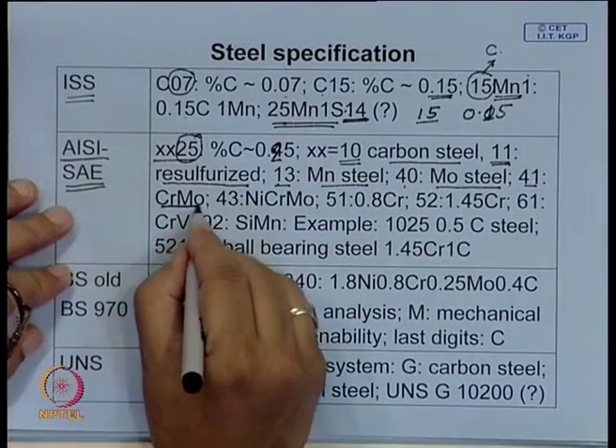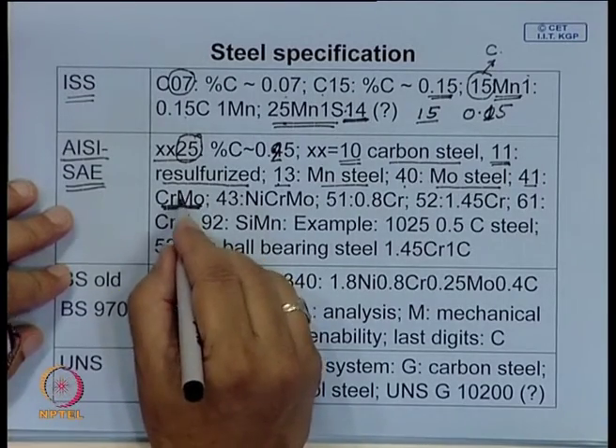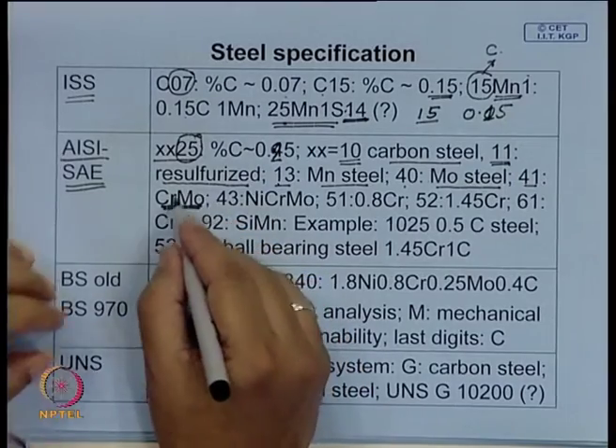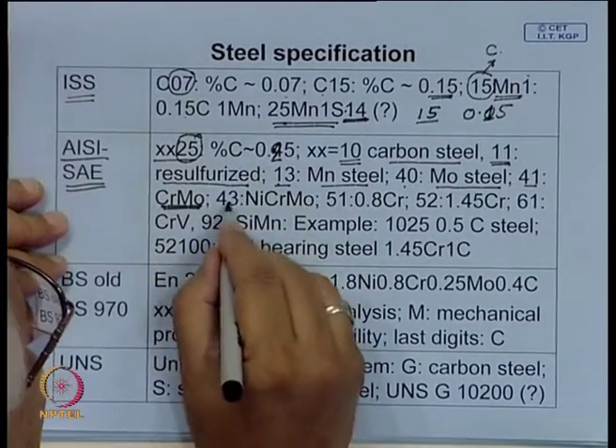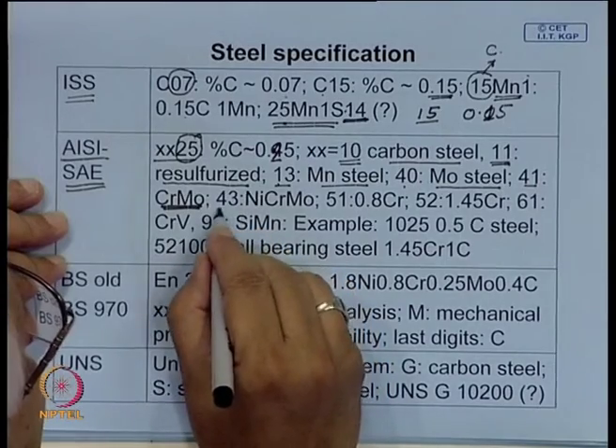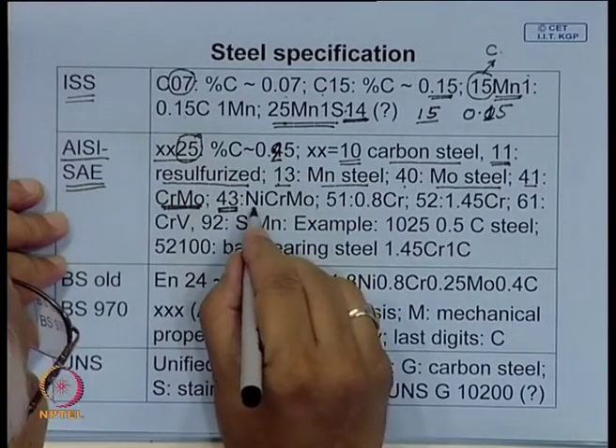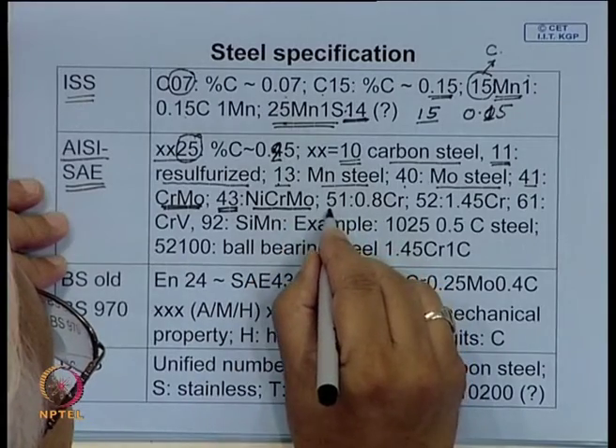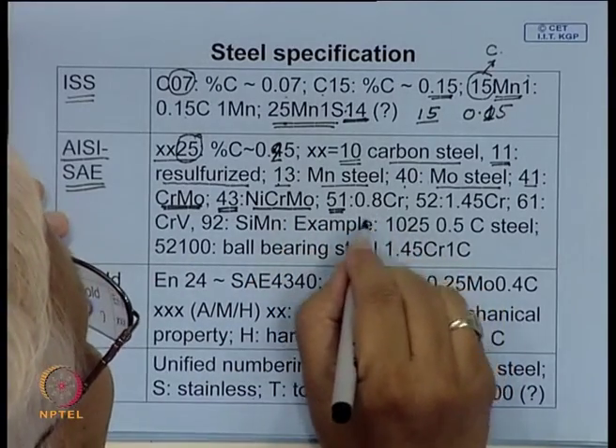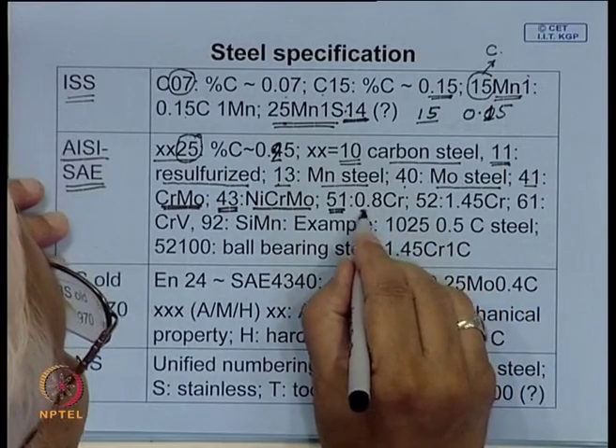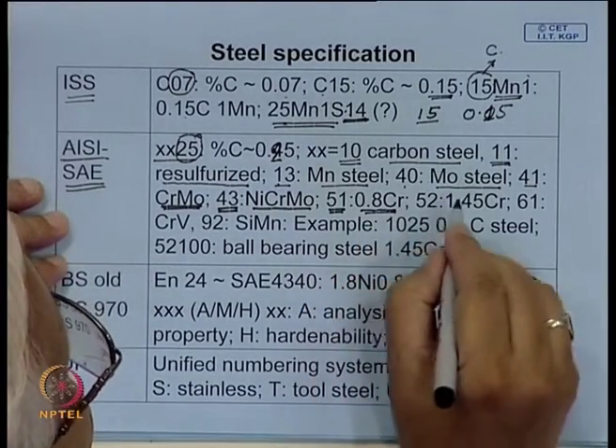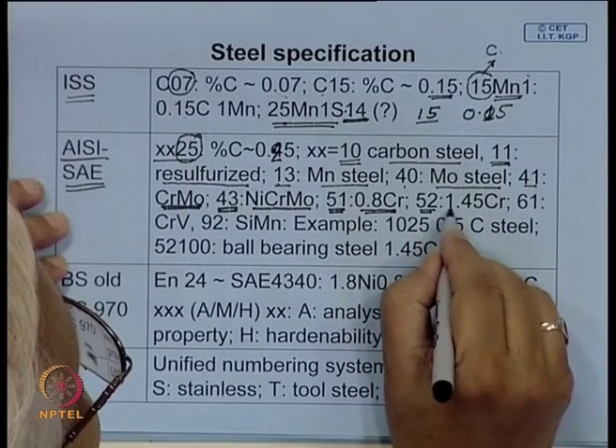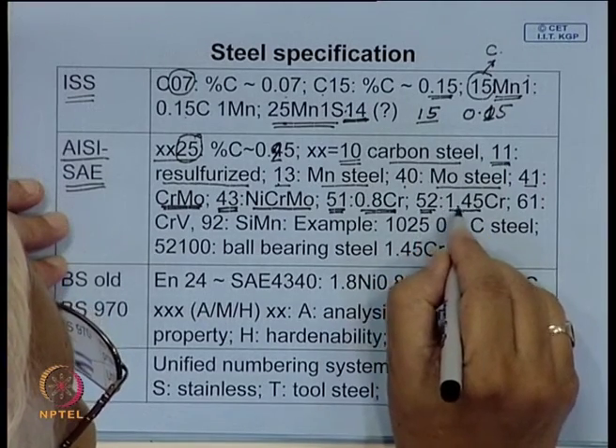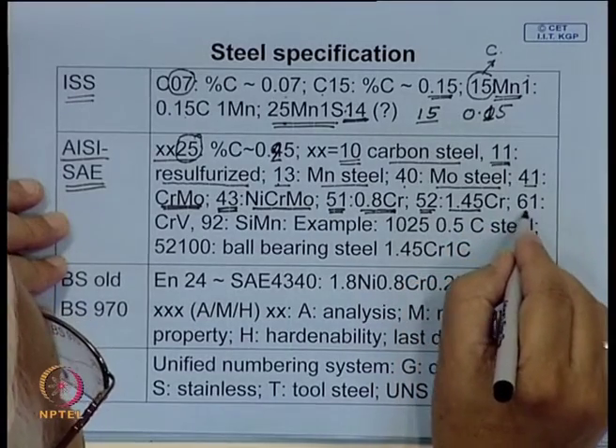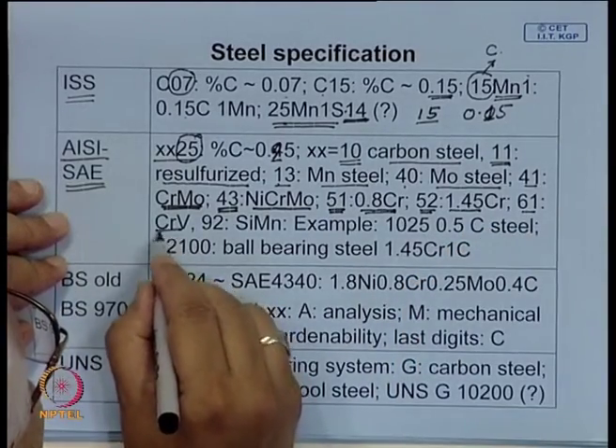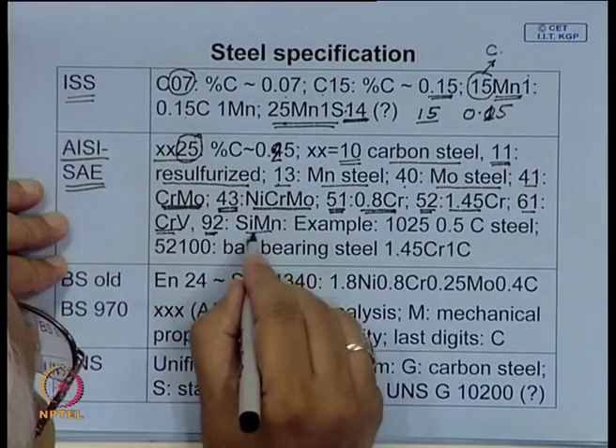41 means you have chromium molybdenum. These are alloy contents, the amount may not be much larger, maybe 1% or 2%. So, 43 means nickel chrome moly. First 2 digits 51 means 0.8 chromium steel. 52 is a chromium steel, a bearing steel, 1.45 chromium. 61 means chrome vanadium steel, 92 silicon manganese steel.